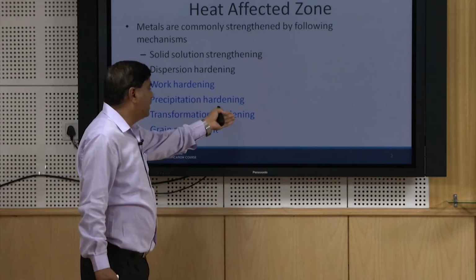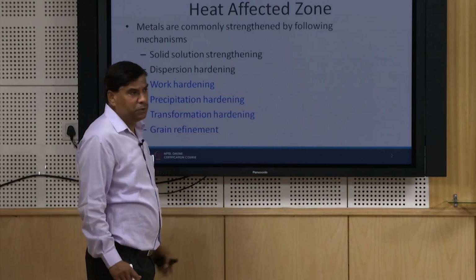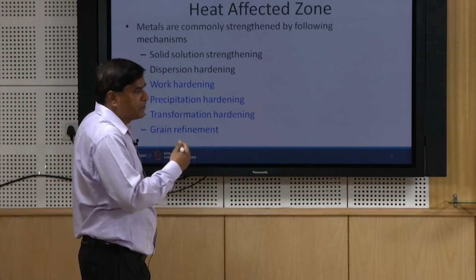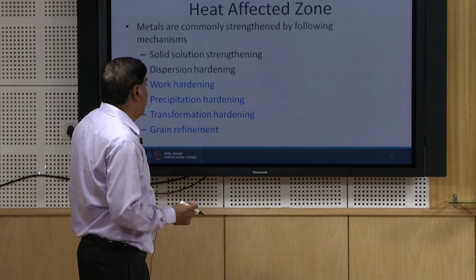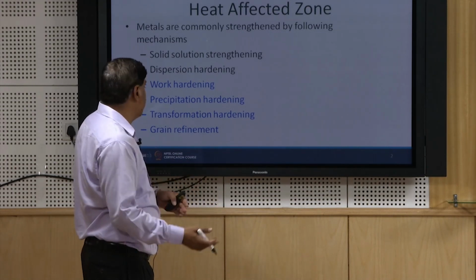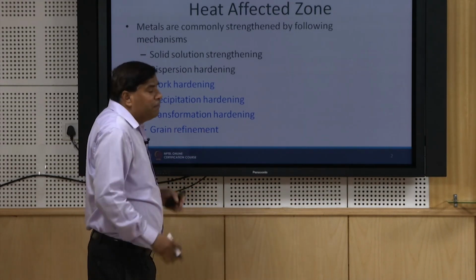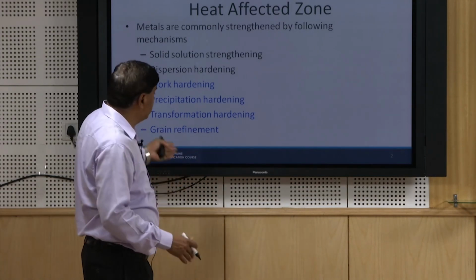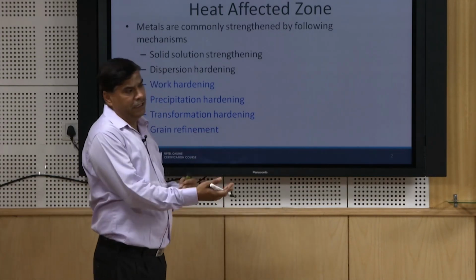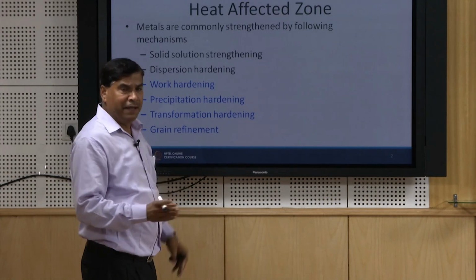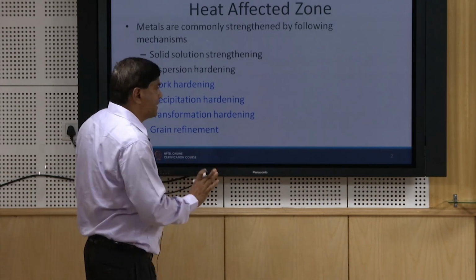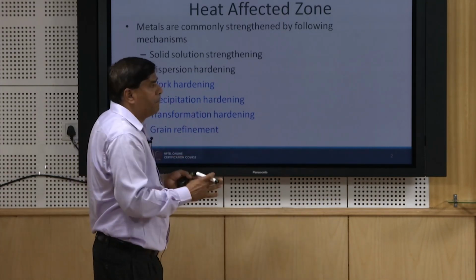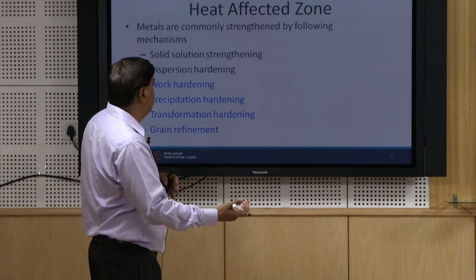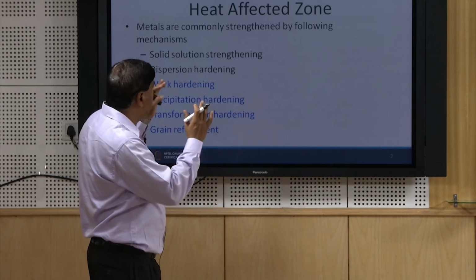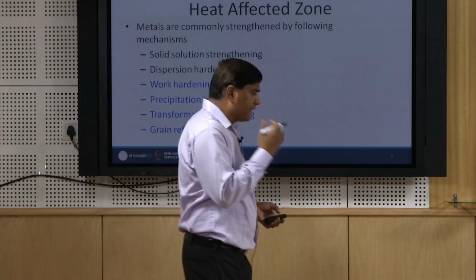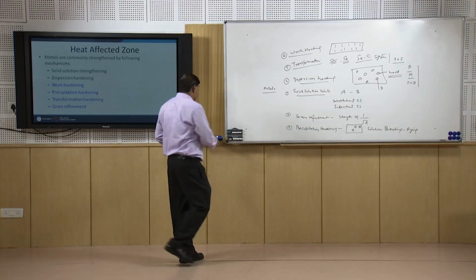In transformation hardening, the high rate of heating and cooling in case of ferrous metal systems mostly causes hardening despite grain coarsening and grain refinement. For metal systems which are only strengthened by grain refinement, the coarsening in the heat affected zone will lower the hardness and strength of the metal system. So, this is a very generic description of the different metal systems and the way things will be affected with respect to the heat affected zone.